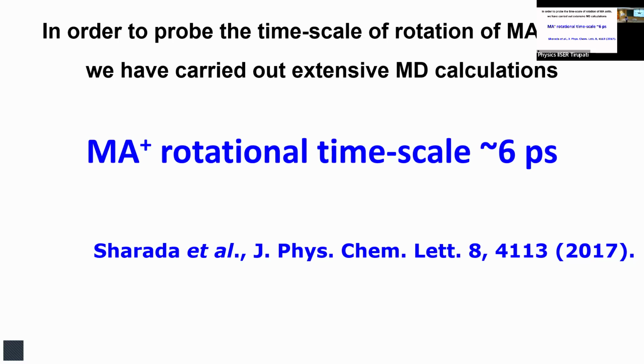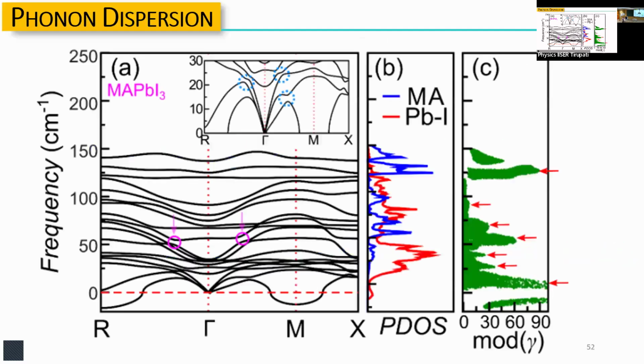And this picosecond timescale is the timescale of the phonons. So this rotating dipole, which has nothing to do with phonons, a completely localized motion, scatters the phonons so rapidly that it kills the phonons, and for the thermal conductivity, you recover the diffusive limit. So it comes to a diffusive limit. And indeed, when you do the calculation, which cannot describe this full rotation but talks about the incipient rotational modes, we find that, this gets technical, I'll skip that, but basically there are signatures in the phonon calculation that indeed these rotational motions of the MA are scattering the phonons very, very strongly, giving rise to tremendous amount of anharmonicity, which essentially means that the lifetime of the phonons is very, very short. Phonons don't live to be phonons for long enough. And that's why thermal conductivity is so low.